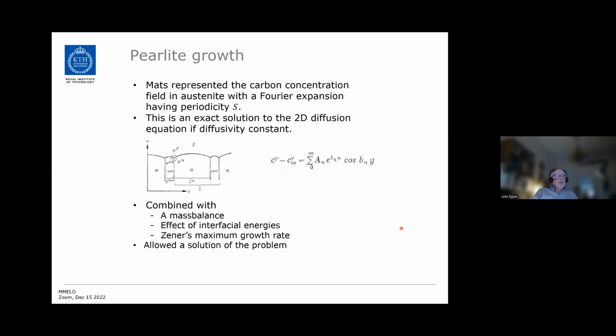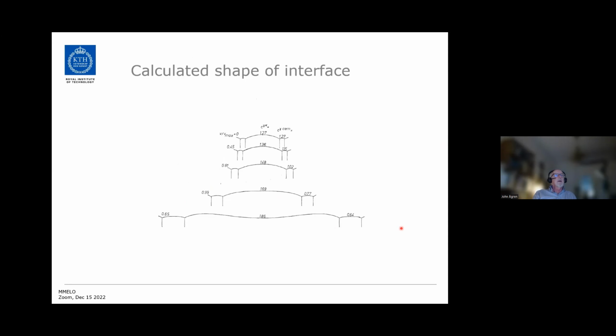And he combined that with the mass balance and the effect of the interfacial energies and the maximum growth rate principle. And then he could solve the problem. And after solving the problem, he could then calculate the shape of the interface. And this is a shape for a different lamellar spacing. And this is in, well, reasonable agreement with micrographs.